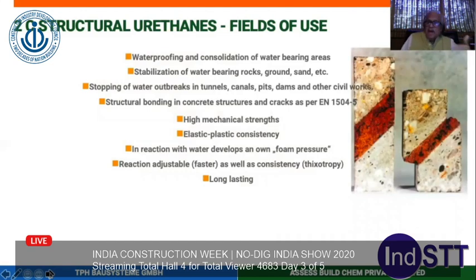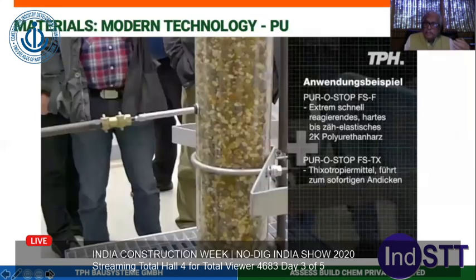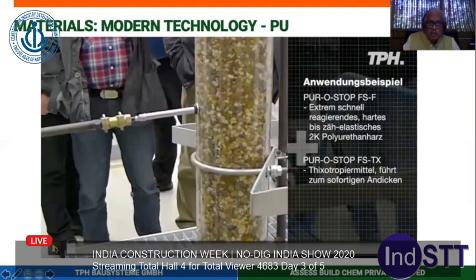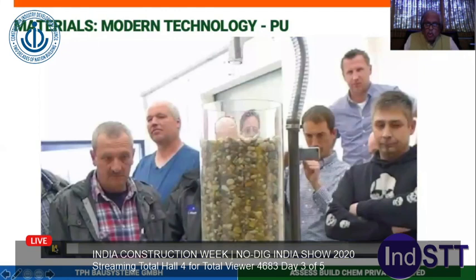They have a very high bond strength, very high shear strength. And this is very, very important either for soil consolidation or force transmitting cracks. And these are the materials. So foaming polyurethanes alone are not the end of the story. It is just the beginning of the story. Even if you do the temporary stoppage of water by one component foams, for permanent stoppage of water, you will have to go for two component structural injections.